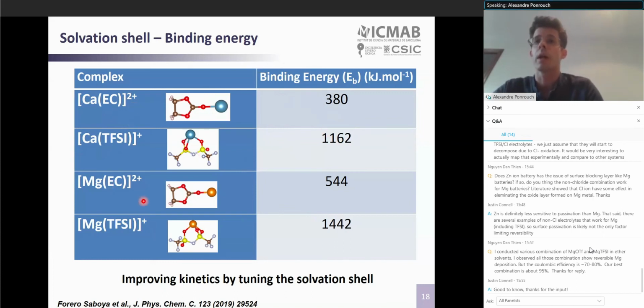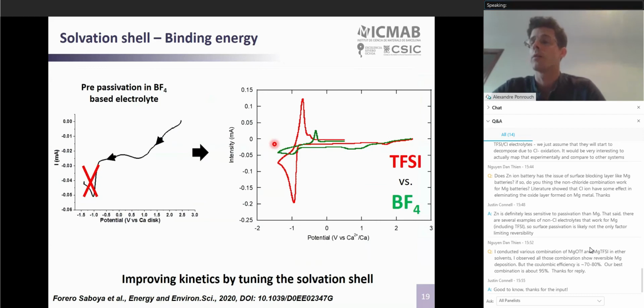And now comparing the calcium and magnesium, you can see that there is a slight increase in terms of binding energy when coming from calcium to magnesium. So now coming back to the previous results, we can start to rationalize the results we obtained previously.